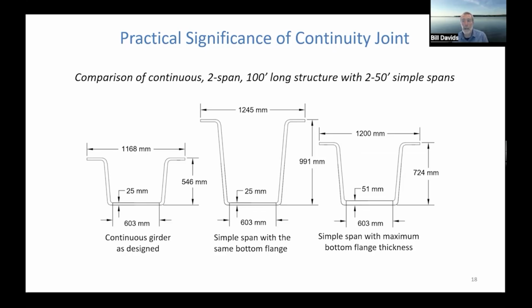In other words, we don't have the continuity joint. And as designed as a continuous structure, the cross-section of the girder that we designed to meet deflection and stress requirements is shown on the left. It's 546 millimeters deep, so that's about 22 inches. And then there's another 8 inches of deck on top, a 25 millimeter bottom flange.